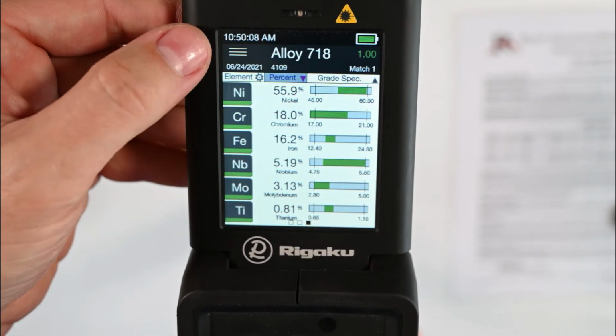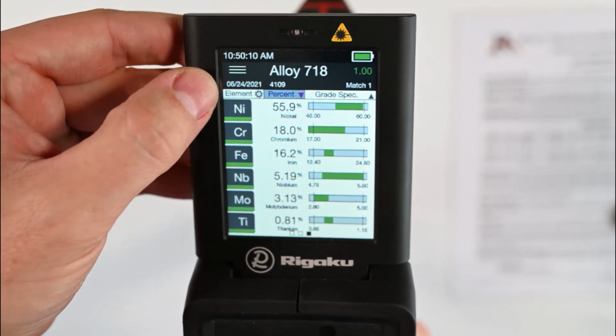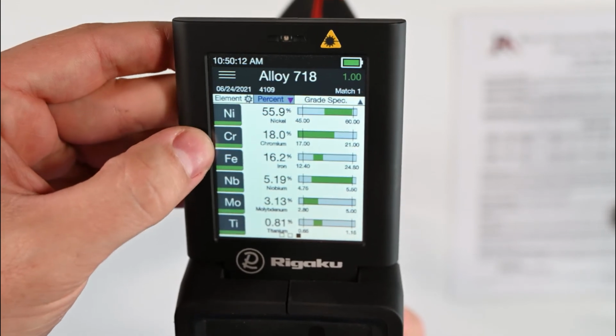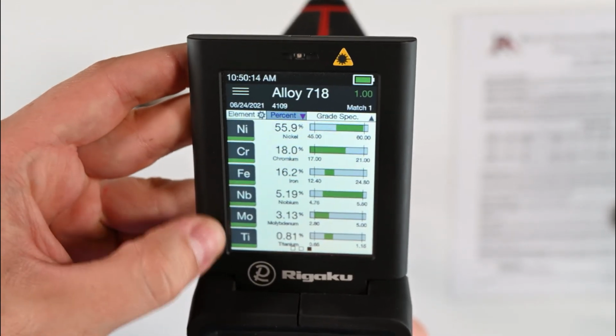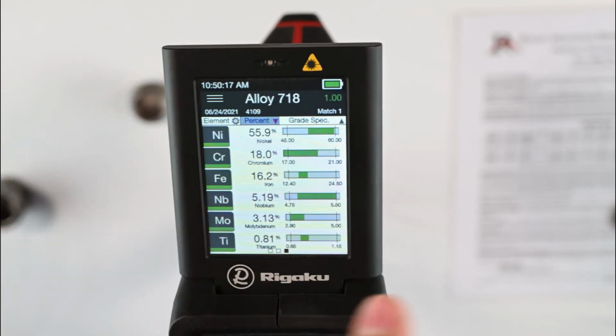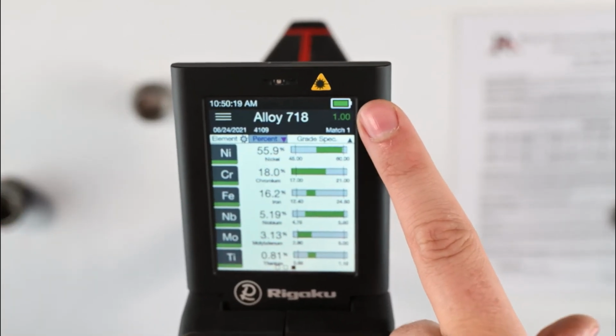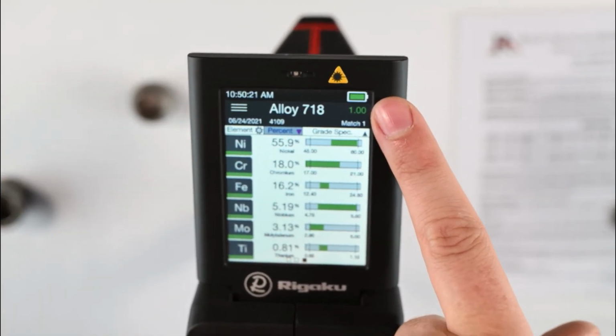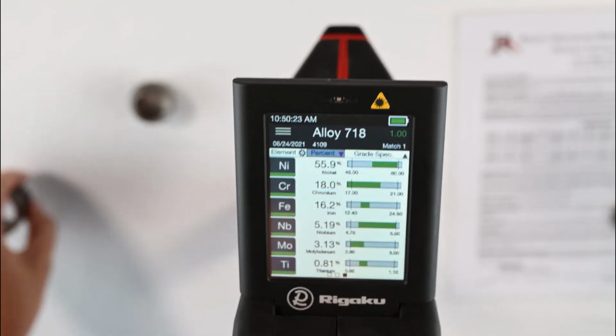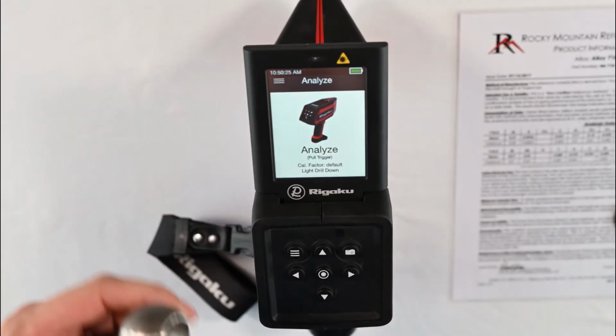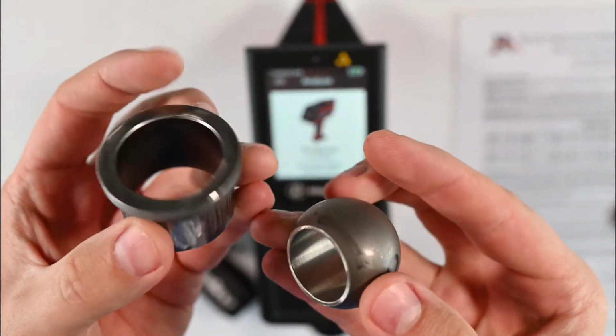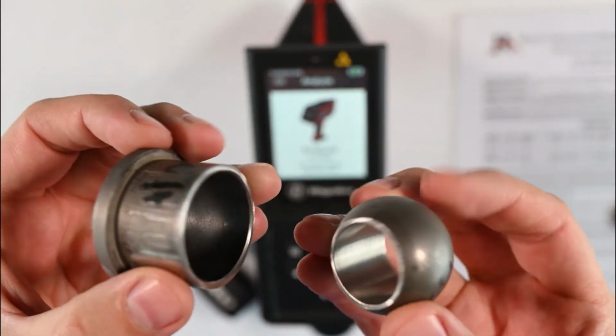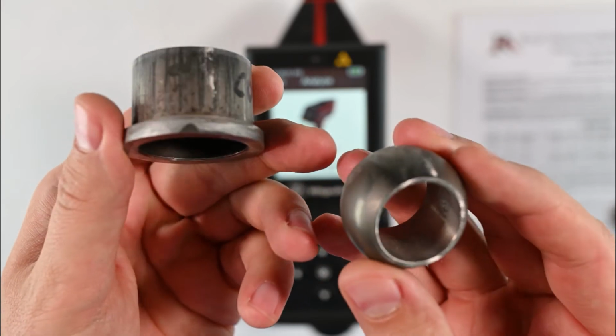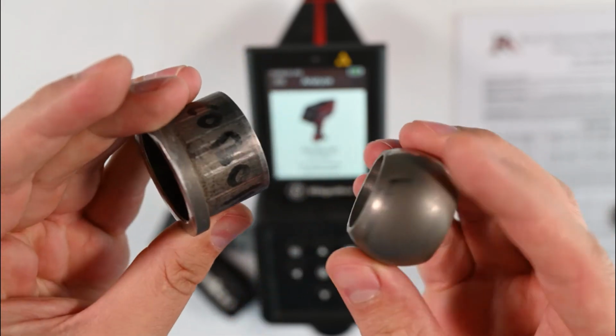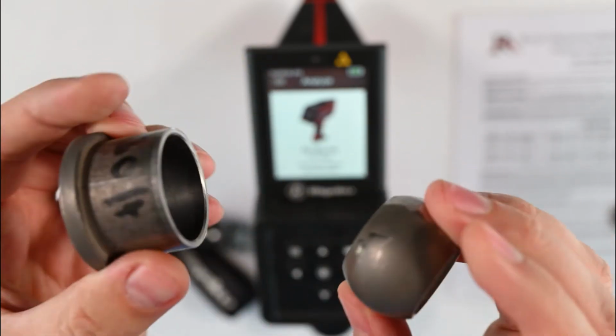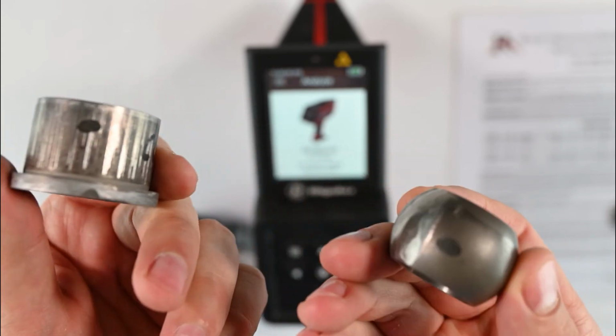So, all right, INCONEL 718, or alloy 718 as we call it in our gun. You can see that the chrome, iron, niobium, moly, titanium, they're all right in that range, a pretty tight range for this grade. Over here, we've got 100% match. So we know this is not cobalt, that this is a 718. All these parts come out of high temperature applications or corrosion applications where that nickel really helps them survive their environment, and they're common in the scrap industry, and this is big money for the scrap industry because of the high nickel content.